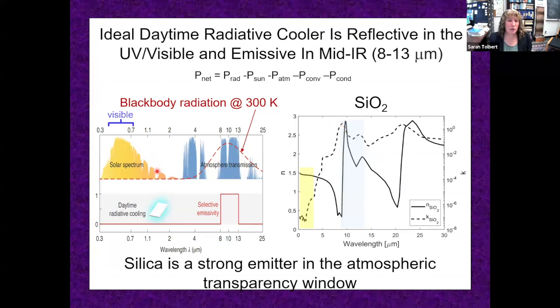Here is the solar spectrum. So this is wavelength in microns. We have to pick microns because we're going over a very big range. Here is the visible, sort of 400 to 700 nanometers, or 0.4 to 0.7 microns. And the solar spectrum goes into the near IR. So you want something that does not absorb any light in that region, and in fact, actively scatters away all of the light that comes from the sun.